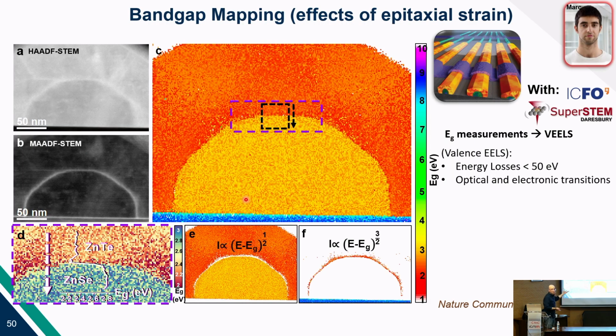And this is what I showed you before. You can go further and calculate the band gap here and see that the strain at the interface, which is visualized here in this type of image, this is a special type of mode in STEM that is showing you which are the parts that are more strained.